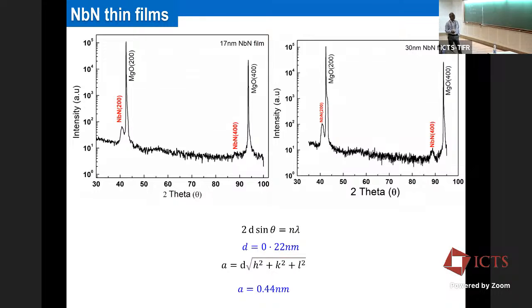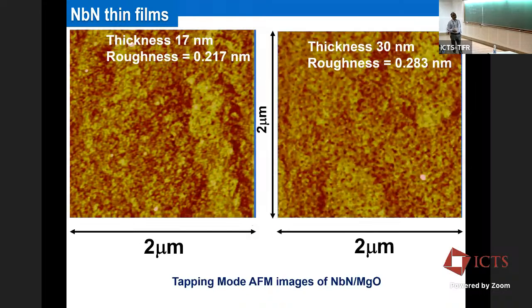This is while we were optimizing our NbN film. Here you can clearly see that we are only obtaining the NbN 200 phase. This is a film of 17 nanometer thickness, and this is a film of 30 nanometer thickness. As I don't have RT measurements, I was using the magnetic property measurement system, sorry.